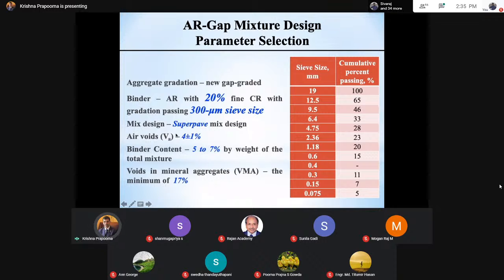The other thing that we did, we blended a binder. So we customized a binder for our own sake. If you go to CRME 55, CRME 60, I told you it's about 8 to 12%. I told you that will not be fitting the AR definition. So we went in with a new design. We started all the way from 5%, 10%, 15, 20, 25, 30. So we tried all of this. This is a PhD work. You can imagine how much work the candidate had to do. We actually reached a saturation point at about 25%. So 20, 25, 30, they all reached a saturation level in terms of stresses and strains.